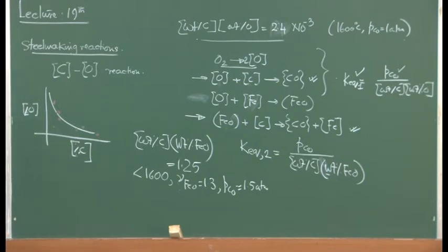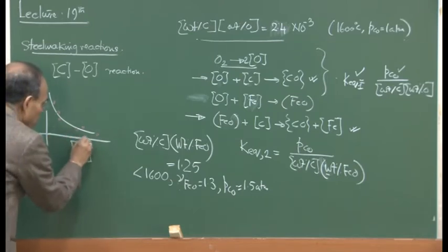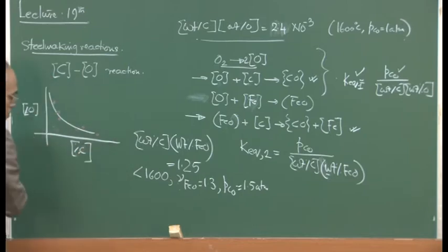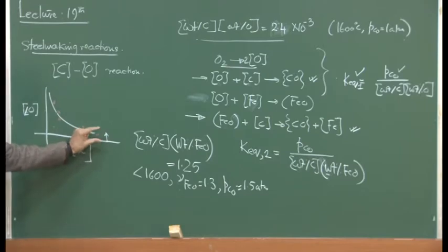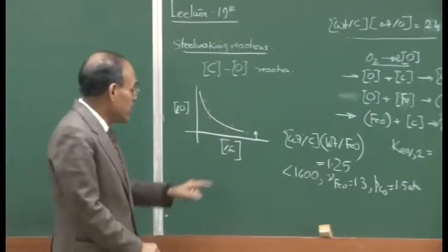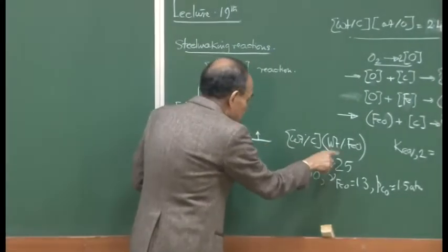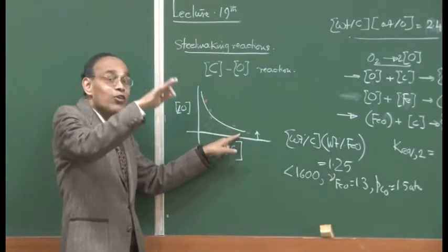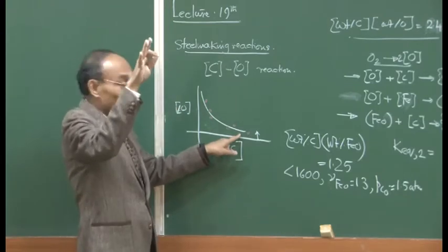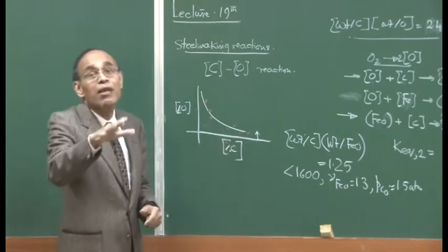So this gives you the clue that so long as the metal has high carbon content, the melt will not contain much oxygen; it will only contain this much of a dissolved oxygen. Similarly, on the basis of these reactions, we can also conclude that the FeO content of the slag is also going to be smaller during the initial period.